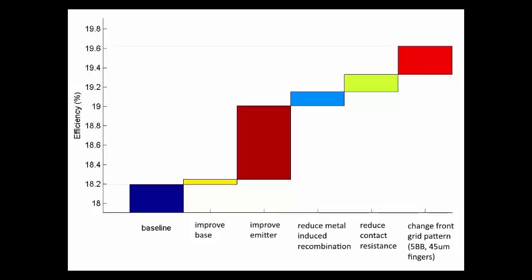Switching the front metal paste or improving the emitter and print firing processes can reduce the front metal induced recombination and front contact resistance to more respectable values, with room for improvement by about 0.3% absolute. So this gives us a kind of roadmap towards how to get our efficiency up by more than 1%. In this case, the optimization of the passivated emitter is key.